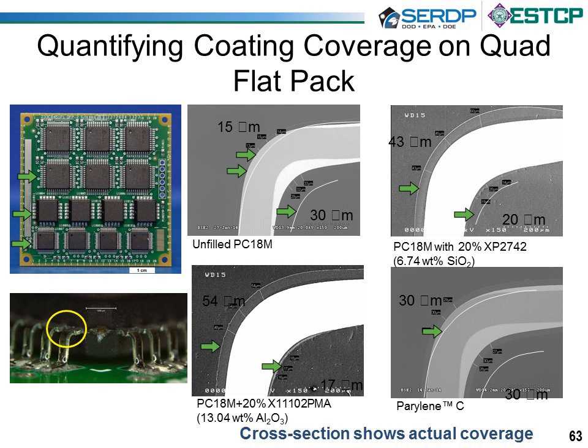And, of course, the Parylene, just 30 microns front and back. It was just 30 microns, which is a typical target thickness. Usually that goes between a little under 20 microns to about 25 microns for typical assemblies.